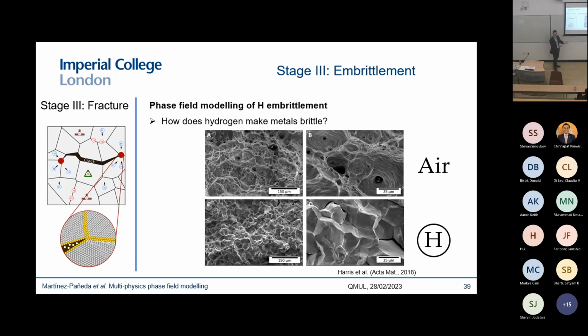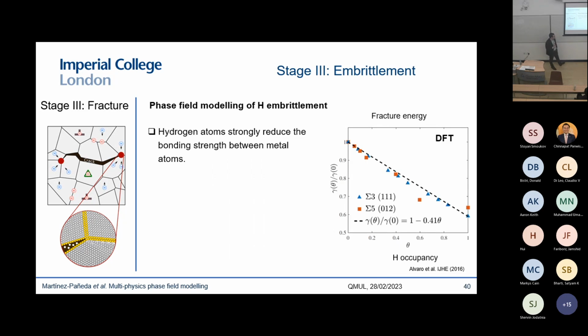So, of course, the key question when trying to come up with a mechanistic interpretation is: how can it be that a metal that fails in the absence of hydrogen in such a ductile manner, with micro-void cracking mechanisms, fails in such a brittle fashion in the presence of hydrogen? You can see here these cracks originating on the grain boundaries. And in my opinion, there are three key ingredients to understand this. The first one is that when you do atomistic calculations, this is DFT for nickel, for several types of grain boundary, what you see is that hydrogen very significantly reduces the fracture energy. So you can see here that when you have full hydrogen occupancy of the grain boundary, going all the way to 1, you get a 40% reduction in the fracture energy.